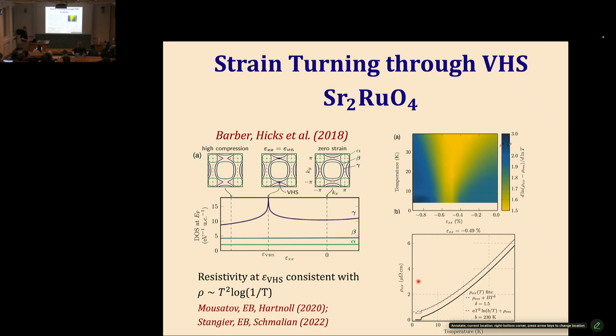And it turns out that as you do that, it looks like t squared log t is fitting the data a little bit better than t to the power 1.5. So we believe we understand the mechanism of the strange metal here. It's not that strange. It's just a log deviation from the Fermi liquid behavior, and it's coming from this pileup of a low energy density of states close to a 2D Van Hove singularity.